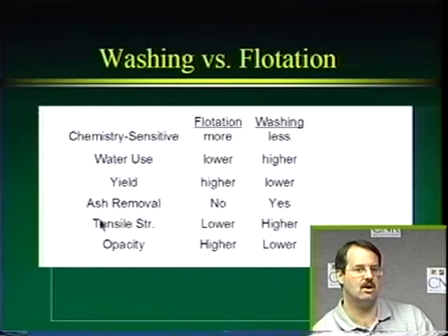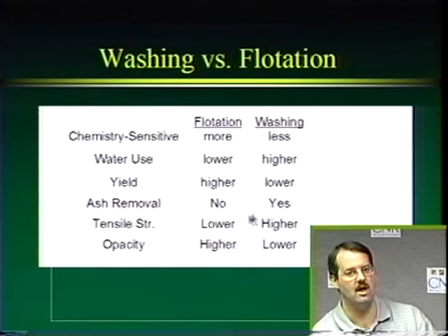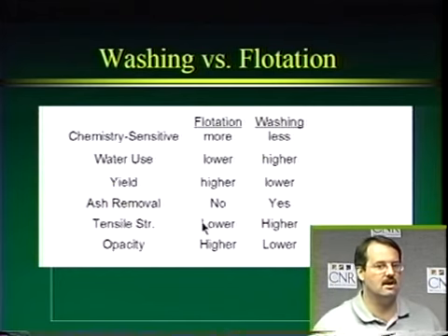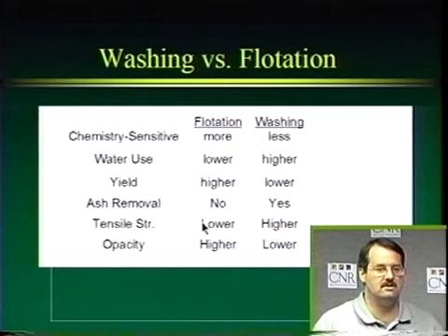Ash actually causes our tensile strength to go down. So if we keep the ash in, like we do in flotation, we'll have lower tensile strength. If we wash the ash out, like we do in washing, then we'll have higher tensile strength. You can see that ash, inorganic material, cannot hydrogen bond with the cellulose fibers, and for that reason, it interferes with bonding and lowers our tensile strength.